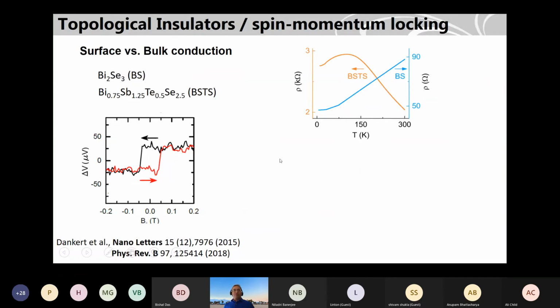So we compared two materials because it is interesting to see where the spin is coming from, whether it's surface versus bulk conduction. So bismuth selenide, as most of you know, is a metallic material, so the resistance goes down with temperature. But BSTS is semiconducting in the beginning, the resistance goes up, and below 100 Kelvin the resistance goes down. So this is actually a good topological insulator material below 100 Kelvin.